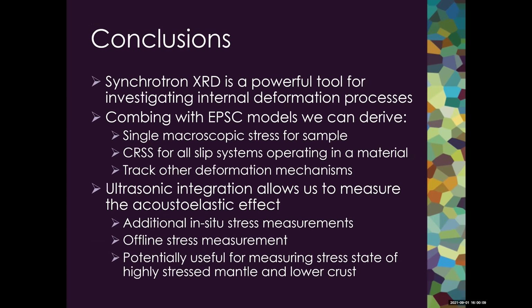And so in conclusion, synchrotron X-ray diffraction is a powerful tool for investigating internal deformation processes in polycrystalline materials. And in combination with EPSC modeling, we can derive a single macroscopic stress for the aggregate, as well as the critically resolved shear stress for individual slip systems operating in a sample. And we can map these parameters across the entire PT space available to us in the DDIA.